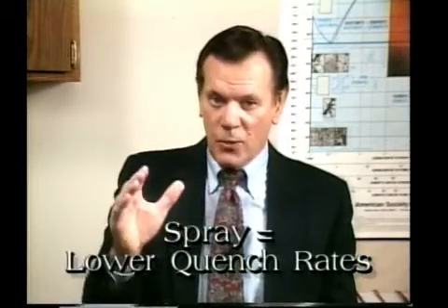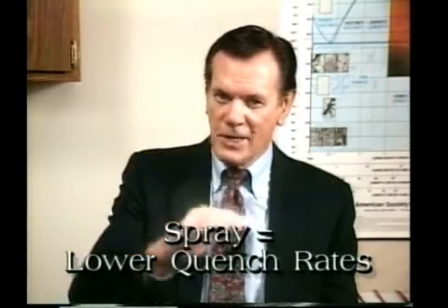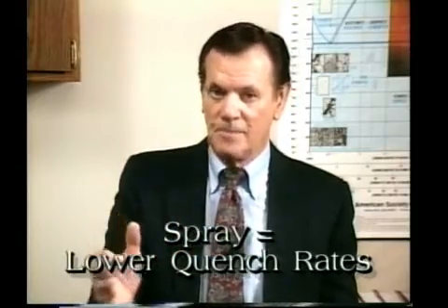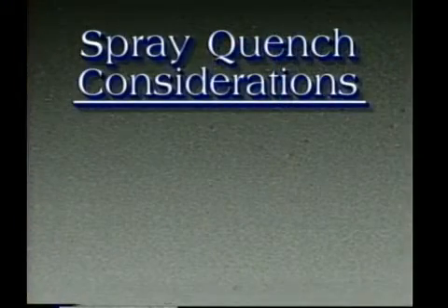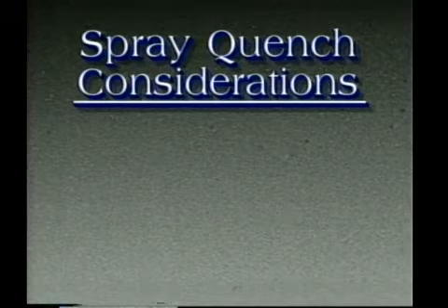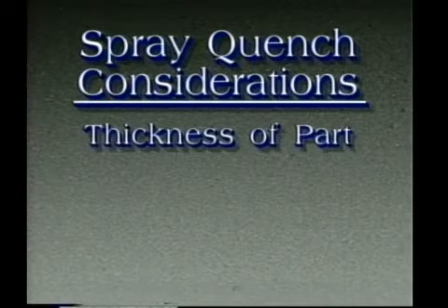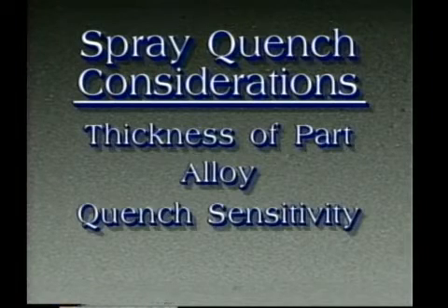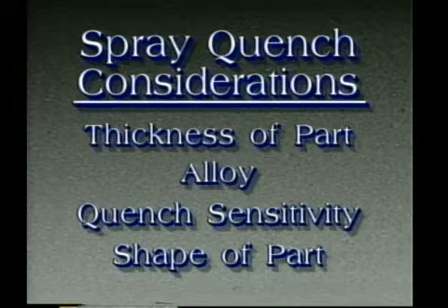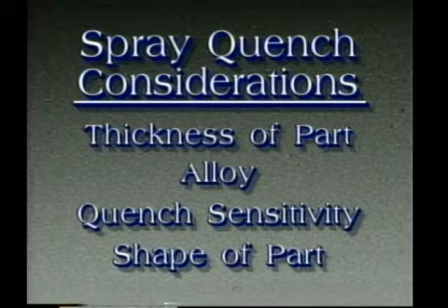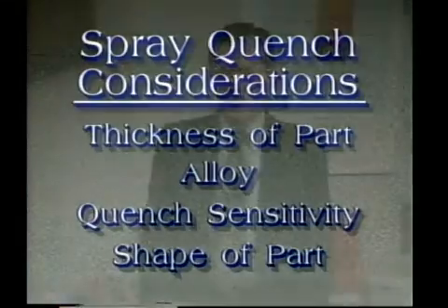As a result, spray quenching can result in a significant loss in tensile properties when the part is later aged, especially when heat treating the more quench-sensitive 2000 and 7000 series alloys. This property loss can be particularly high if the temperature of the water spray is raised above 160 degrees. If spray quenching is considered for aluminum heat treatment, a careful study should be made involving the thickness of the part, the alloy being heat treated, its quench sensitivity, and the shape or configuration of the part to ensure that the quenching is adequate and that a degradation of properties will not occur.